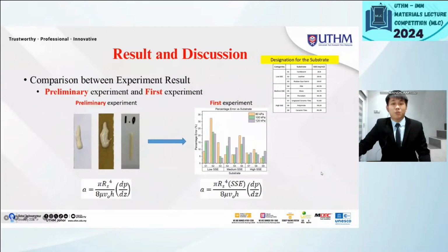For the comparison between the preliminary experiment and the first experiment, the graph indicates that the percentage error decreased after integrating the substrate surface energy into the existing models. In the first experiment, the highest percentage error is 32.50%, while the lowest is 3.75%. These reductions in percentage error are attributed to the decrease in line width, which results from the increased printing speed. With a faster printing speed, the deposition time at each spot is reduced, leading to less silver ink being deposited in any given area.